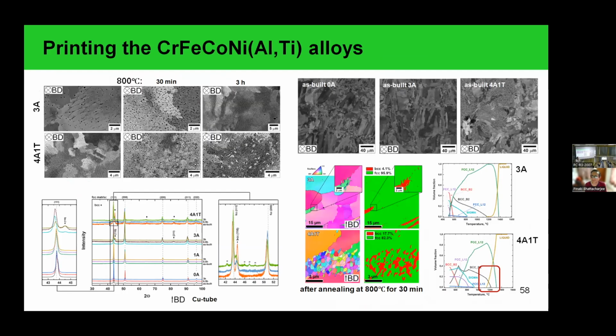Yes, and here again there's the challenge of this way of performing this material. In case of the X-ray diffraction analysis, we can see that there are small peaks which can be associated with approximately 5%, but the problem is that in the additive manufacturing material we have a strong texture, and we cannot directly calculate it from the X-ray diffraction analysis.